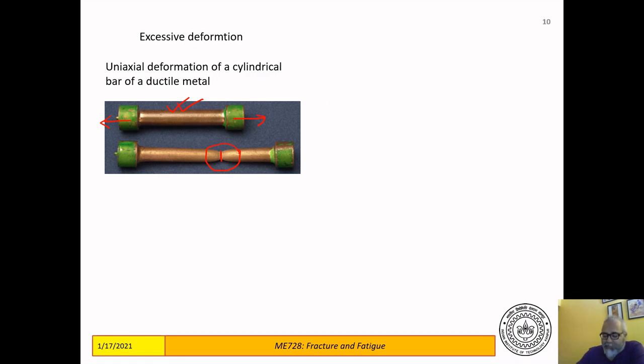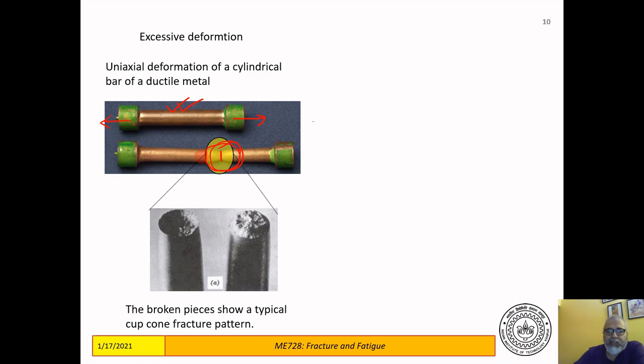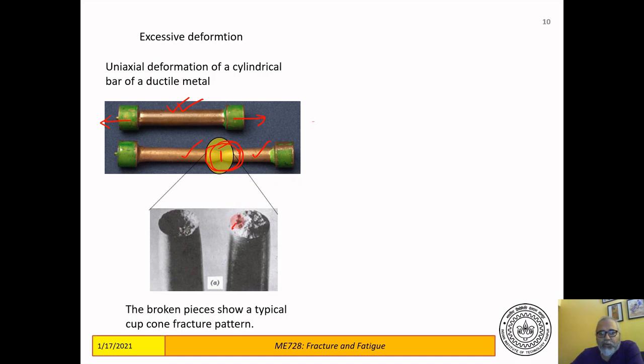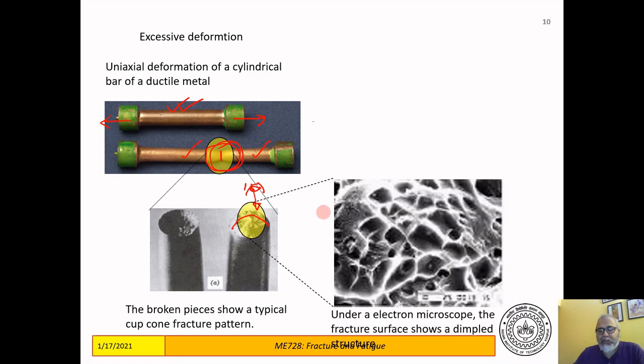Now if you look at this neck part carefully, you will see that the two parts form what is known as a cup and a cone. This part forms the cup, which is actually a depression, and this part forms the cone, which is actually a small hill. So these two fit together. Now if you look at the top view under a microscope, at a small area here, what you will see is a structure like this. This is a typical example of a dimpled structure, which is a hallmark of ductile failure.